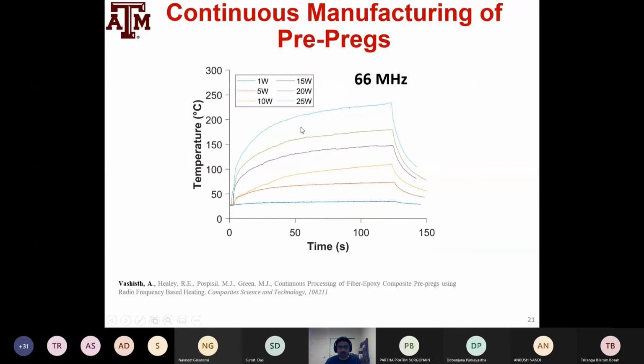So what we saw was that just by varying the amount of input power, you can get up to 250 degrees Celsius within 2 minutes. So this was really, really fast. This is really rapid for curing epoxies. So this was really good. This was really promising, and this is something that my lab plans to pursue in future as well.